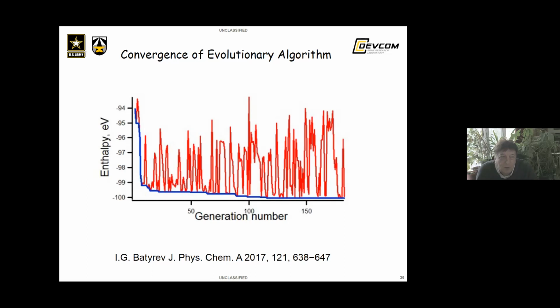This is how typical convergence of the evolutionary process looks like. Enthalpy, minimum enthalpy in blue, versus number of generations. This is one of the central slides of my presentation. Convergence is not variational. Typically, evolution stops when the lowest enthalpy structure does not change for 10, 20 generations, so somewhere here.